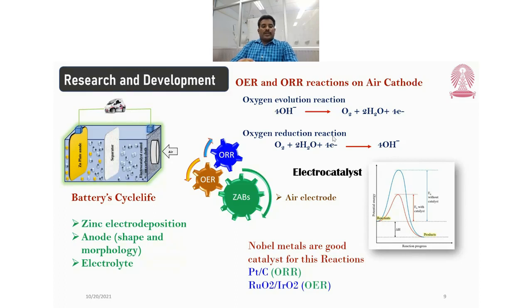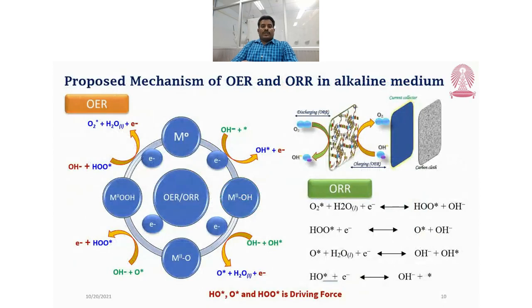Nowadays, people are using precious metal catalysts: platinum on carbon, ruthenium oxide, and iridium oxide are used for this reaction. The mechanism can be divided into two types: the two electron pathway and the four electron pathway. Due to the hydrogen peroxide produced, the two electron pathway is not suitable for this mechanism. However, the four electron pathway is the most suitable.